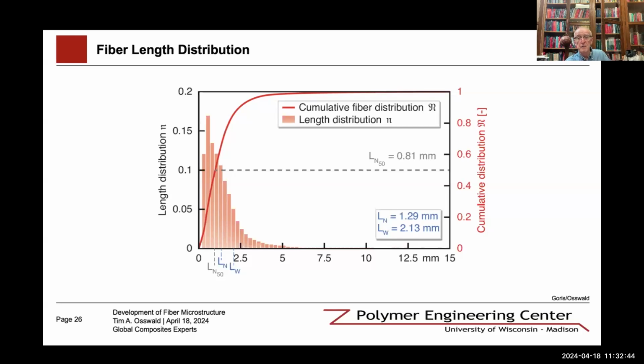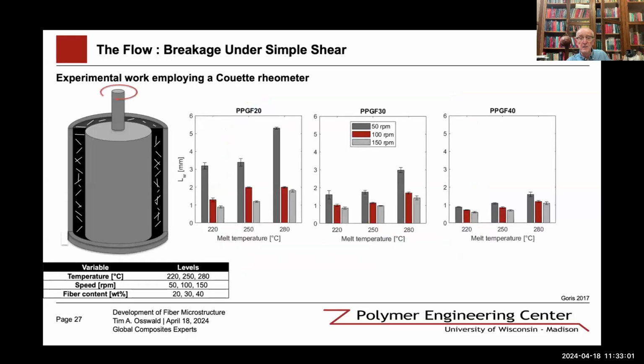And there's the N50 length. That means that 50% of the fibers, in this case, are longer than 0.81 millimeters. And that's, of course, where the cumulative distribution is at 0.5. So that's a way to represent distributions.